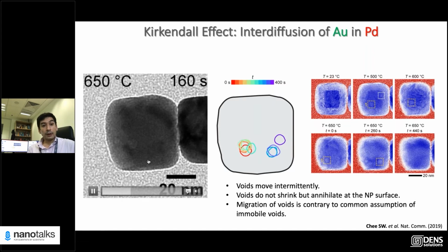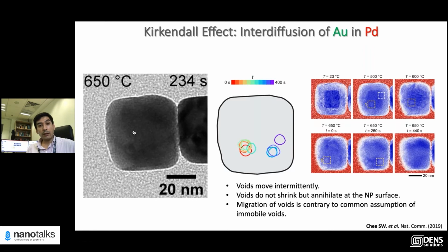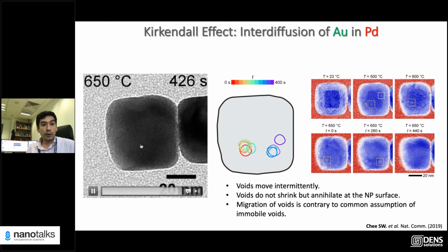And why? Well, because these nanoparticles are single crystal and they don't have a lot of defects. These voids usually tend to get stuck at defects. I'm not going to show the data, but we've done the experiment. When you have a nanoparticle that has a defect, voids get stuck there and then they start growing. And bulk metal is full of defects, and that's exactly why voids get pinned at the defects and can grow. But if you have a very uniform, single crystal nanoparticle, that's not what happens. These voids are very mobile.